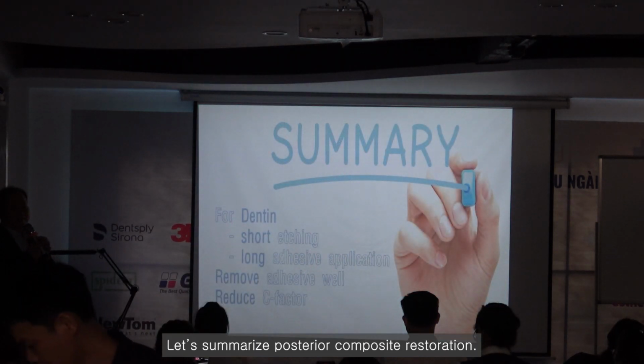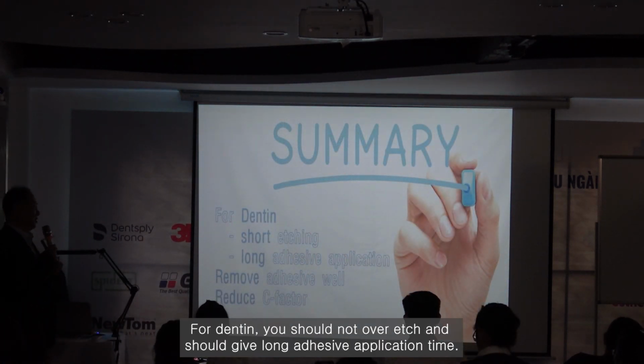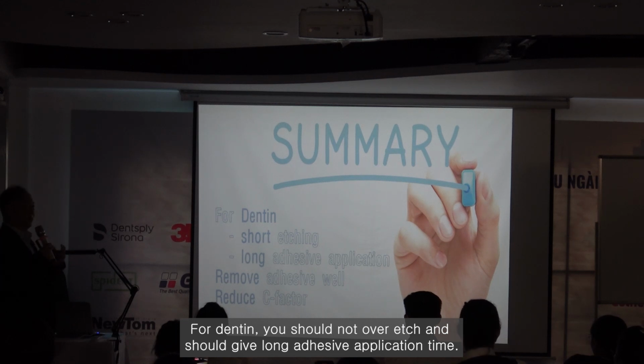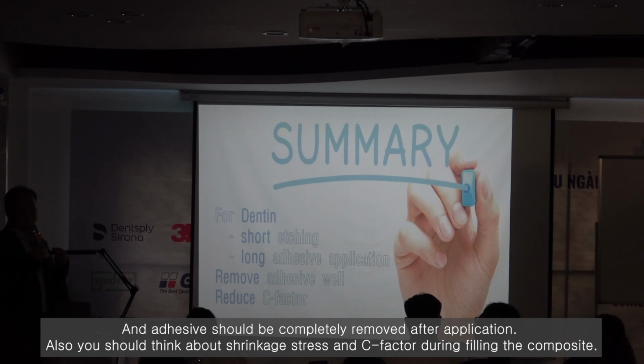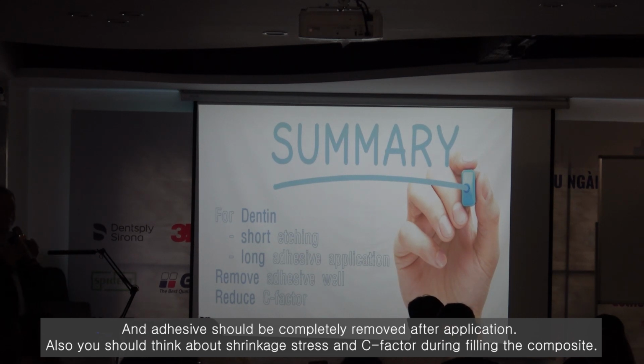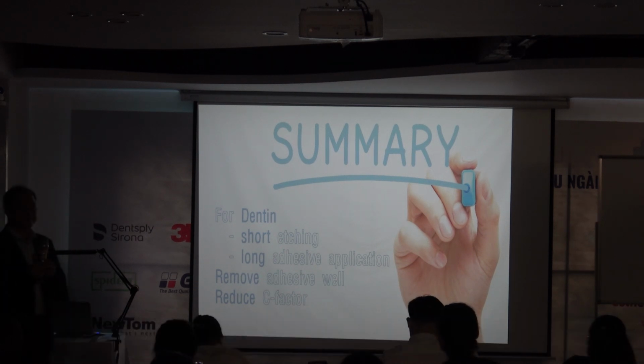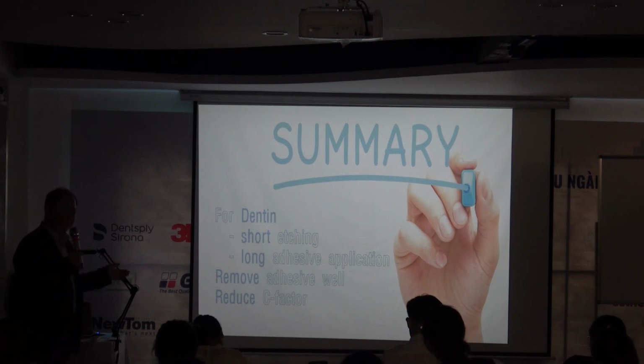Let's summarize posterior composite restorations. For dentin, we should not over-etch the dentin surface and should give a long adhesive application time. And the adhesive should be completely removed after application. And also, we should think about the shrinkage stress instead of always thinking about the C factor during filling the composite. And this is the last slide of the first session.